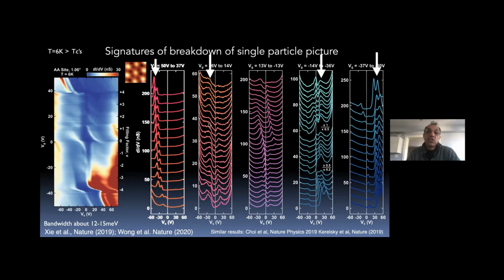But the first message that I want to show you, just from the raw data, is that the energy scale of modification of the density of states spans basically 25 to 50 milli-electron volts, which is much larger than the bandwidth of the system.